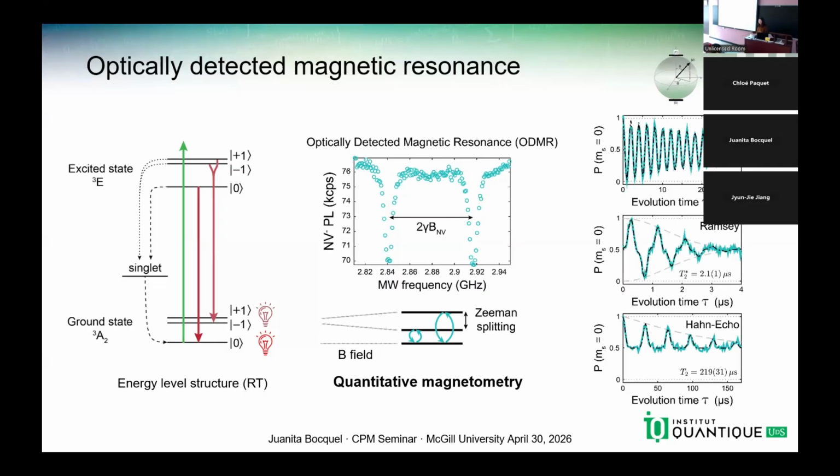If you want to use it as a qubit or as a quantum sensor, you can go a bit further and try to use those microwaves in whole sequences to be able to use it as a qubit. So you manipulate the spins on the Bloch sphere. This is done using first a calibration based on Rabi oscillations, but then you can engineer all kinds of sequences that are typically coming from the NMR community to either make your center, your qubit, more sensitive to the environment or, on the contrary, decouple it from the environment, depending on if you want to compute or if you want to sense.